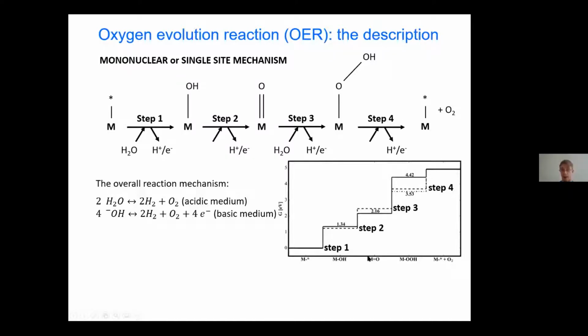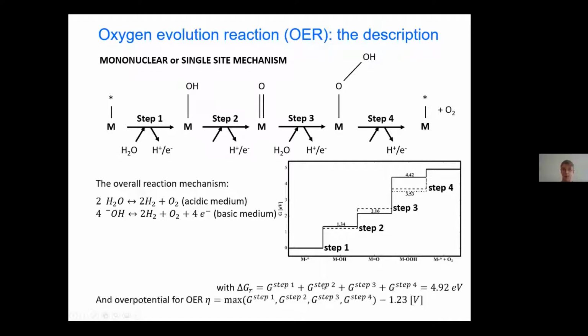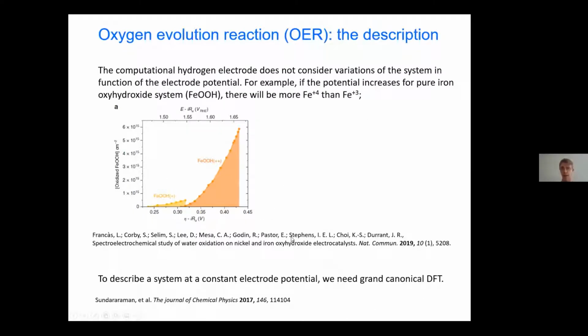And also, we know that the sum of all these steps should be 4.92 electron volt, and we can calculate the overpotential for the OER process by just taking the maximum of the steps minus 1.23, and we get the overpotential in volt. So I have to remark that the computational hydrogen electrode does not consider variations in the system, for example charge, as a function of the electrode potential.